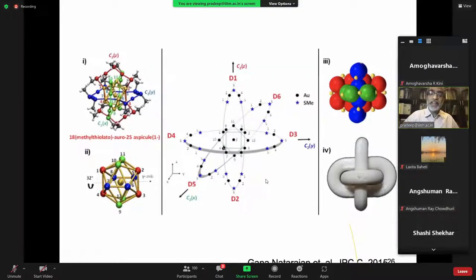This structure is to say that there are rings in this cluster system. And if rings are present in this cluster system, obviously 1 and 4 are more tightly bound than other gold connections, like, for example, the connection between 5 and 11, or 2 and 11. These bonds are in fact slightly longer than these 1, 4 bonds. So it appears that these rings are really present, which allows these cluster systems to open and close very fast. And that is why chemical reactions are becoming so fast.